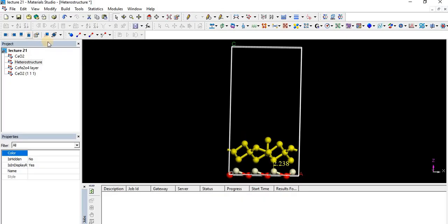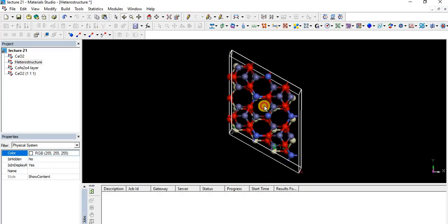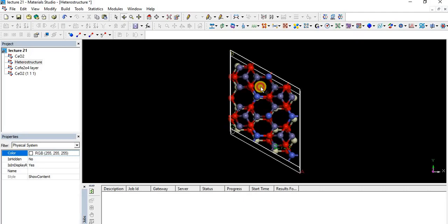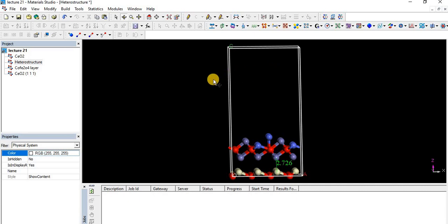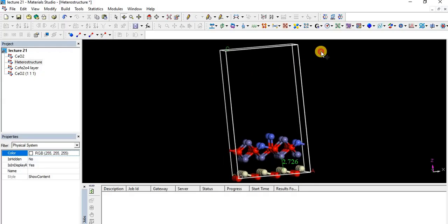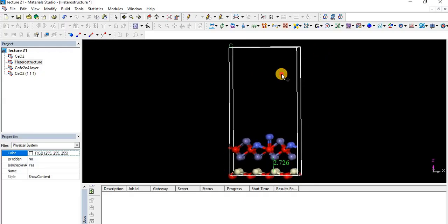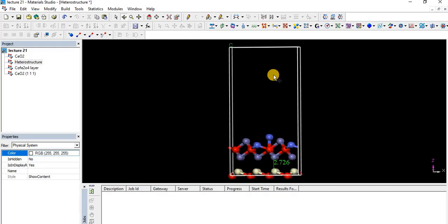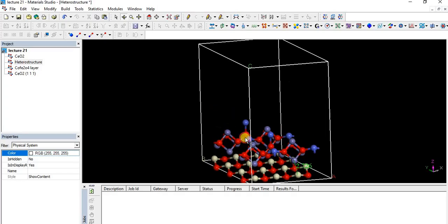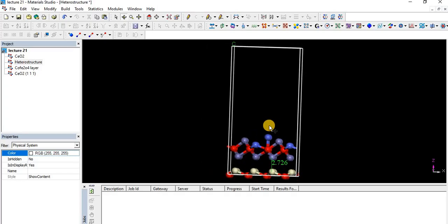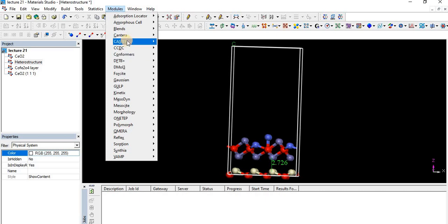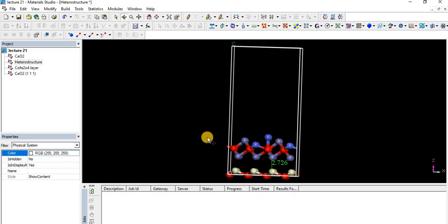It's all about heterostructures and how to make them. Let me revise. Firstly you have to pick both structures individually and then you have to optimize them. After that, make a slab of each, like in 110 direction and 100 direction. After that, simply copy one layer and paste on top of the other, and then using the movement options set the upper layer or lower layer. You will get your structure. Then simply use the CASTEP module or DMol3 module to optimize the structure. Thank you very much. If anyone has any question, please feel free to ask via comment.